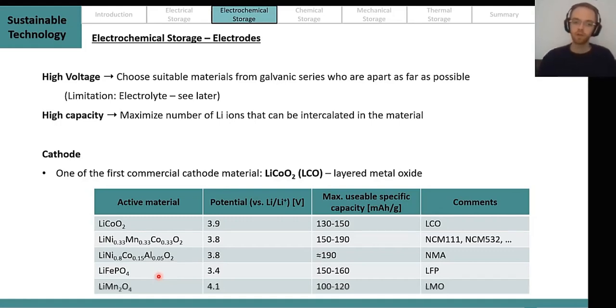There are two other materials which are to be noted because we avoid some environmental impact here by using iron instead of nickel and cobalt, and manganese. So we're simply using cheaply and easily available iron. However, this then leads to a lower cell potential and also typically to a lower usable capacity. So this is the so-called LFP. And the last class basically also uses very cheap manganese. So this is the lithium manganese oxide with a relatively high potential of 4.1 volts, but a very low usable capacity. So this is the so-called LMO.